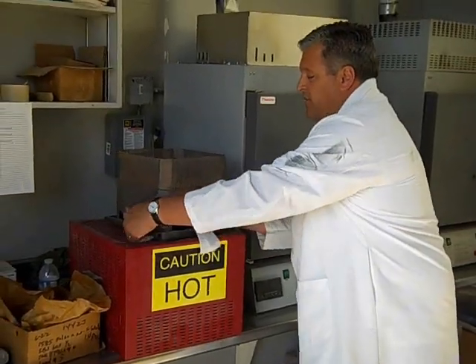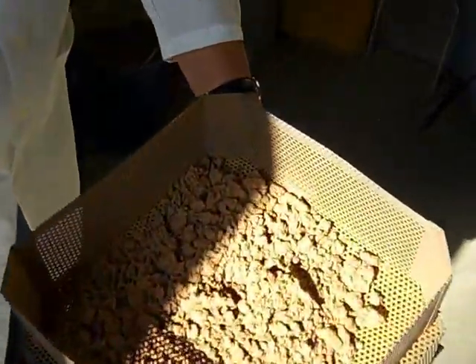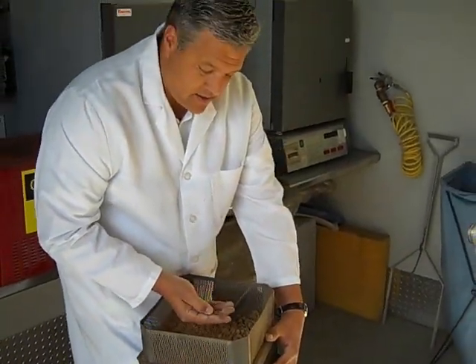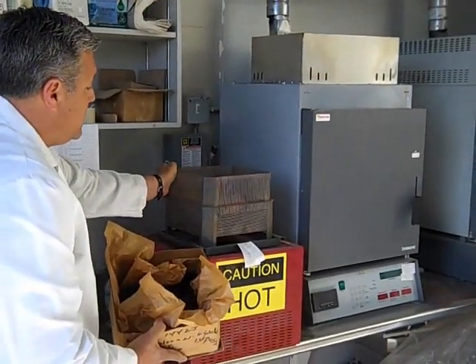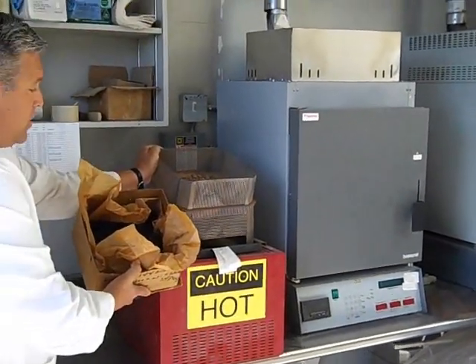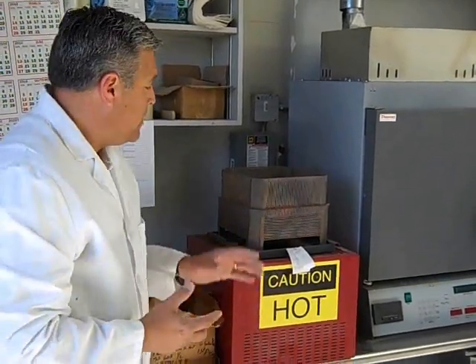We get a sample from the field, and after it gets burned off it begins to look just like this. This is the breakdown of the actual aggregate itself without any oil in it. We break it down into its individual sizes, shape, and numbers, calculate percentages, and make sure it's right. We have a tan-colored sample here and a dark oil sample — the oil part is burned off. The difference in weight between the two lets us know how much oil was used, and that's the really important part of the mix. Like making a cake that calls for a certain amount of eggs or flour, we require a certain amount of oil to make it work. That's exactly what we test here — it's an ongoing test for all our streets.